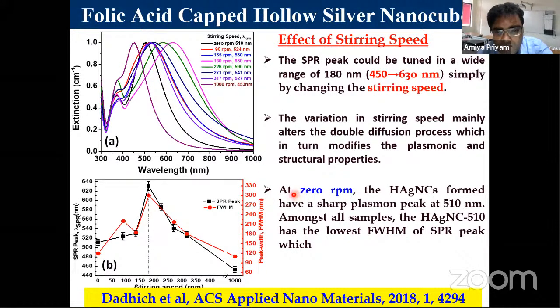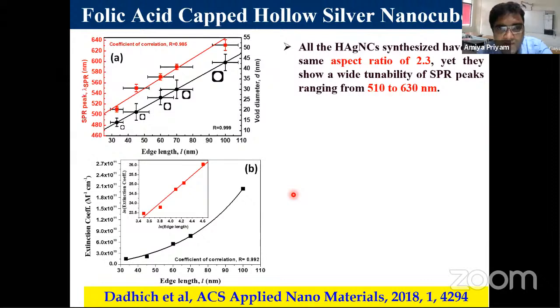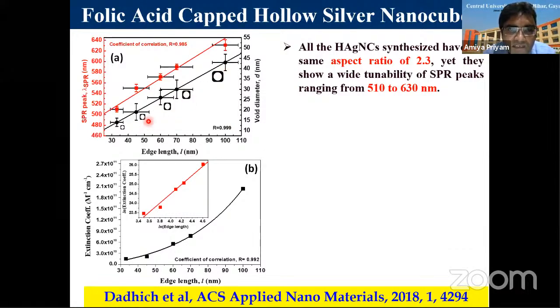So these are the optimizations that were done for the folic acid capped hollow silver nanocrystals. And here again we have made an empirical scaling law based on our observations. What will be the ratio of inner diameter to outer edge length in these edges? So we worked out edge length versus SPR shift. This has been worked out.